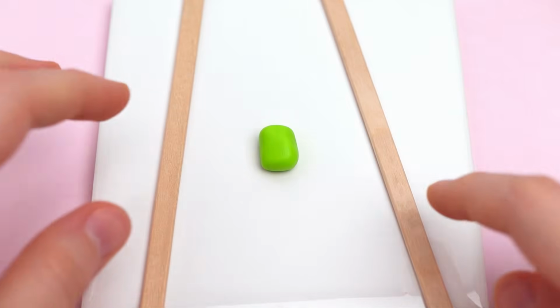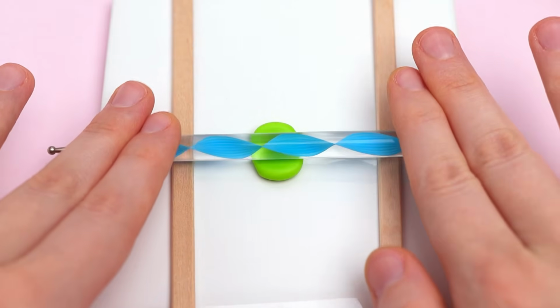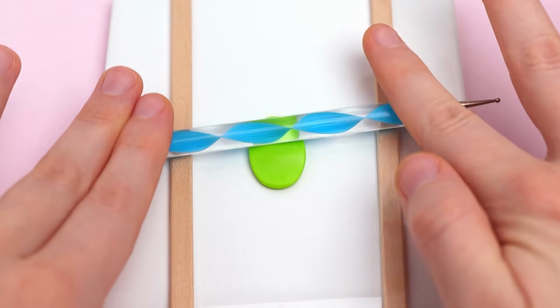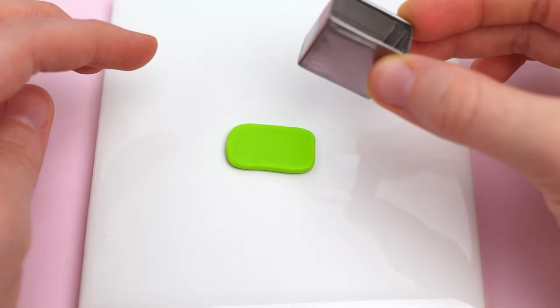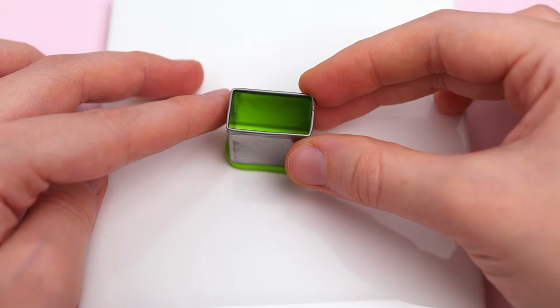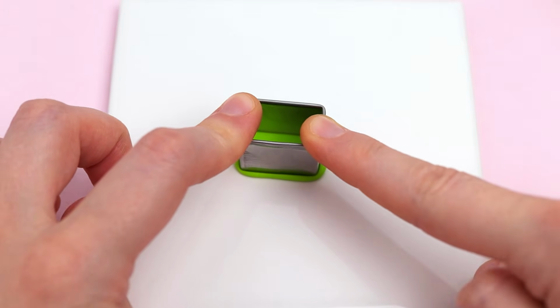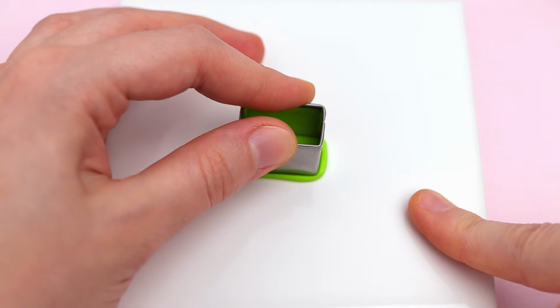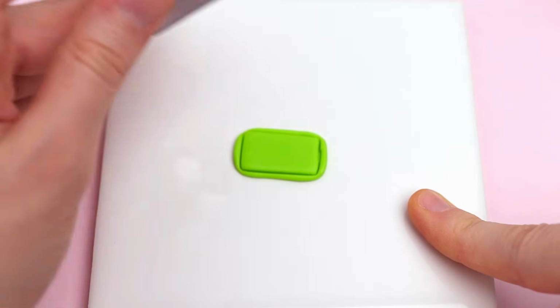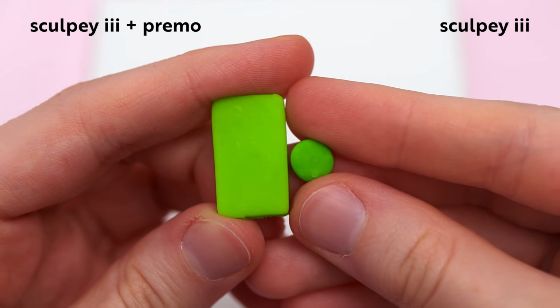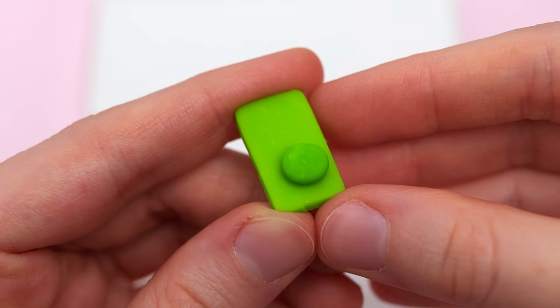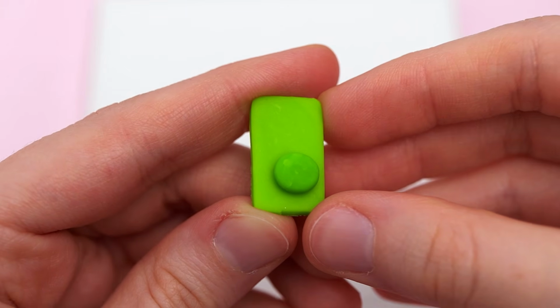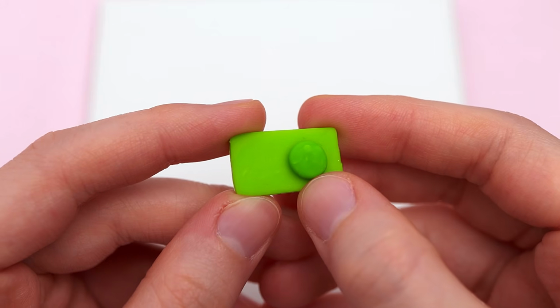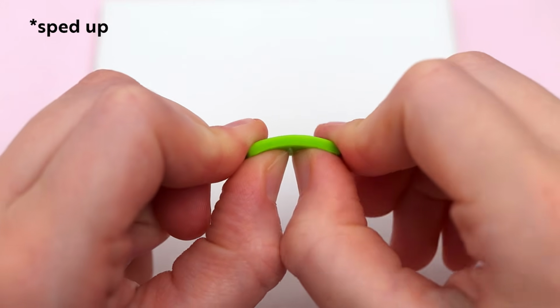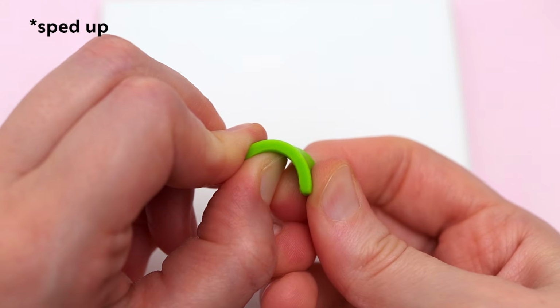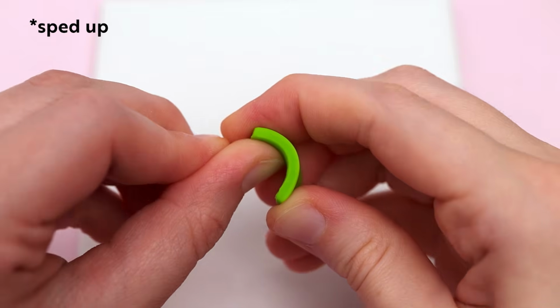Personally, I always use Sculpey Primo for this because it's strong and the raw consistency is easy to sculpt with. And I use translucent clay so that the Sculpey 3 color remains almost exactly the same. But again, you do not have to use translucent. If you do care about preserving the color, here is an after baking comparison between the translucent mix and regular Sculpey 3. And the clay will be significantly stronger than Sculpey 3 on its own.